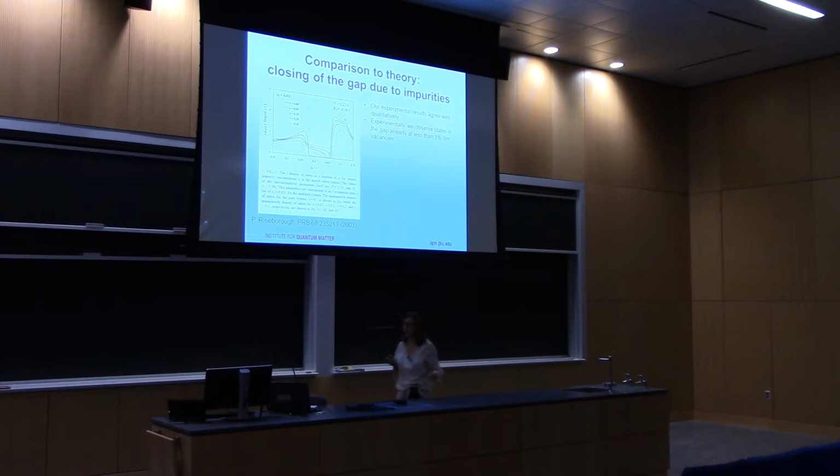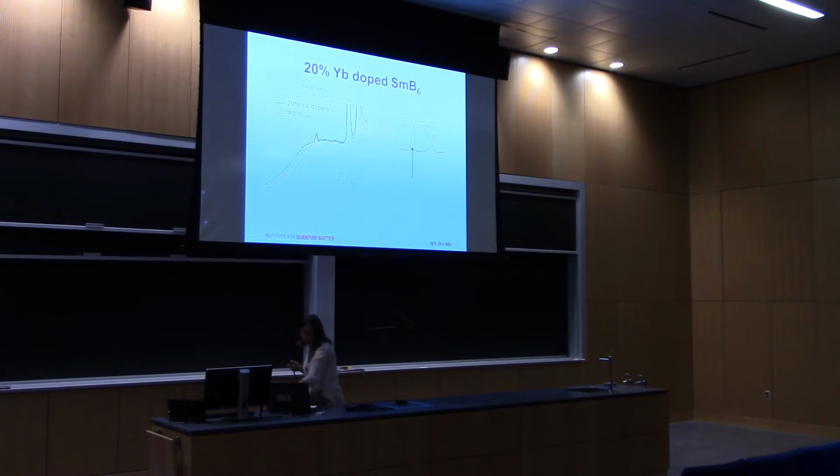It's interesting to mention that we also had a crystal with 20% of ytterbium doping, and the effects in Raman scattering of samarium vacancies or of ytterbium doping are actually similar. We start to have enormous acoustic phonon features, due to the different masses of these atoms, and the intensity tells us how many local defects we have in the lattice.